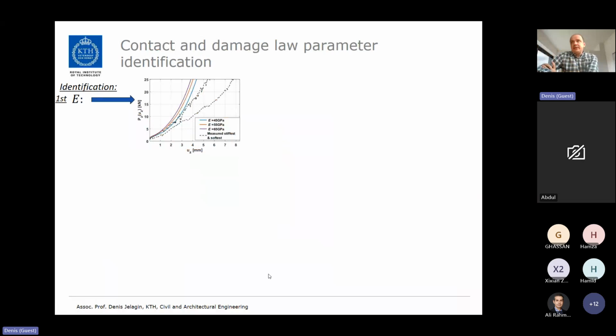As a first step, we need to identify parameters for the contact and damage laws, and we use the same functional shape identified from previous studies. Instead of running a bunch of indentation tests, we are reasonably confident in the functional shape of our contact and damage law. So we have 4 parameters. Young's modulus is identified by fitting discrete element simulations to the initial part of the measured response. The dashed lines here are the lab measurements, and we have our discrete element simulations without any aggregate breakage. We see which Young's modulus for aggregates gives the best fit at the beginning of the loading process.